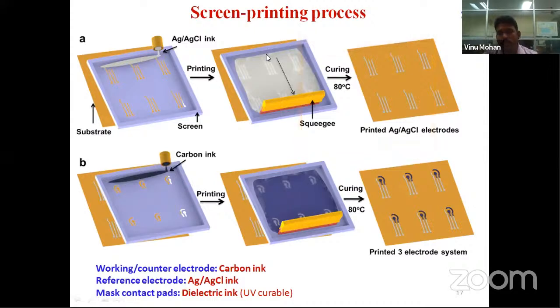Earlier I mentioned we have to use AgCl ink and carbon ink. We have to prepare a stencil or a screen that has the design of the electrochemical sensor, and we apply the ink on the stencil, and using a squeegee we can move the ink on top of the stencil, and this leads to the printing of that ink on the underlying substrate. After curing the first print, then we can choose the carbon stencil.